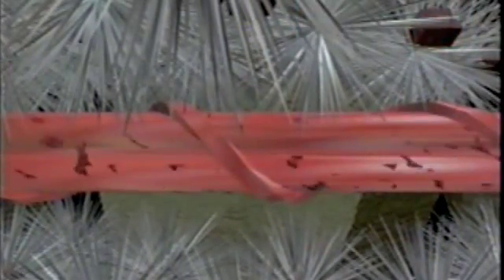From the outside, water and oxygen also penetrate, thus increasing the rusting reaction of the reinforcing bars. The rust which forms occupies a volume of about 6 times more than the metal from which it originated, and so causes the cracking and expulsion of the concrete cover. Let's imagine we can blow up this picture and get a better look at the causes of the deterioration. As you can see, in this case, carbonation has caused considerable damage, causing the cover to come away completely.